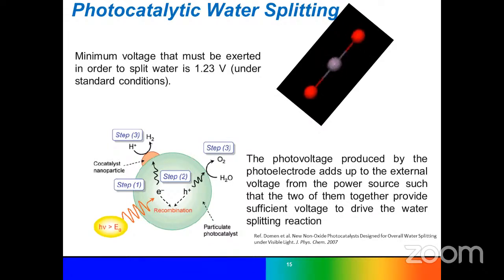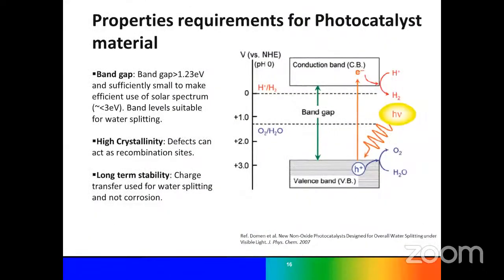So that's why the selection of the material which has a very low band gap and tuning of the band gap, and which has low recombination property, that material should be used for this purpose of water splitting. So here, some of the properties that a photocatalyst requires: one is the band gap, another is high crystallinity, because defects create recombination states. That means hole and electron combine in the recombination part, which will reduce the amount of the produced electricity. So high crystallinity is required, where there will be a defect-free surface, and long-term stability.